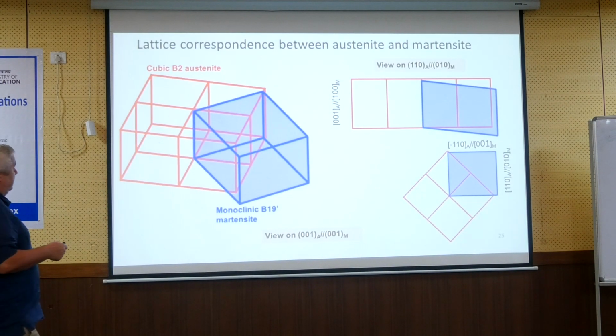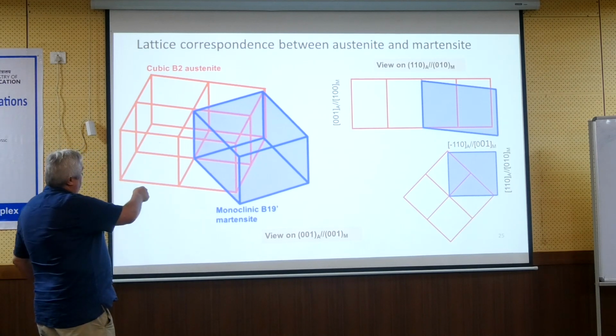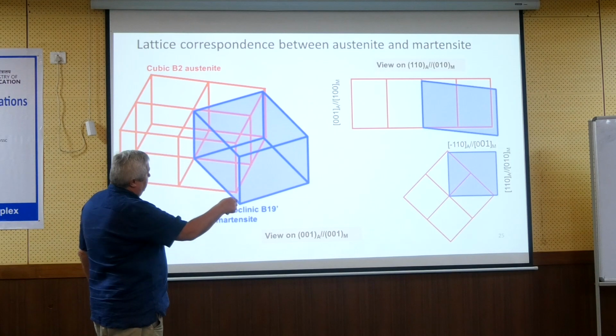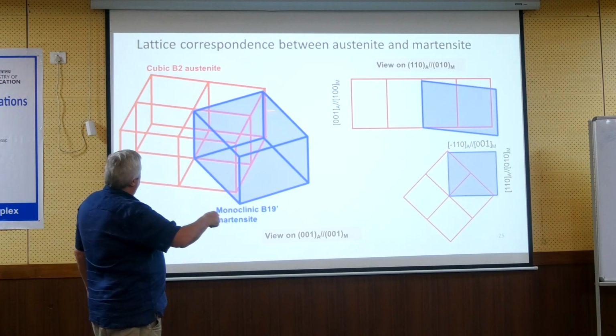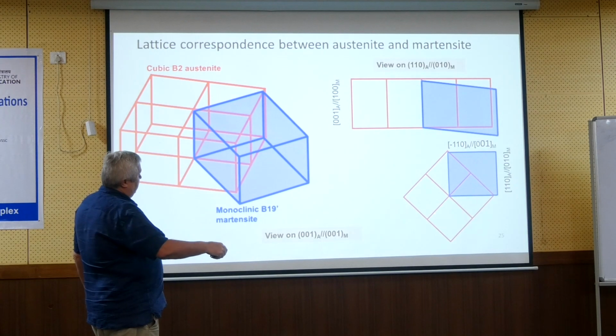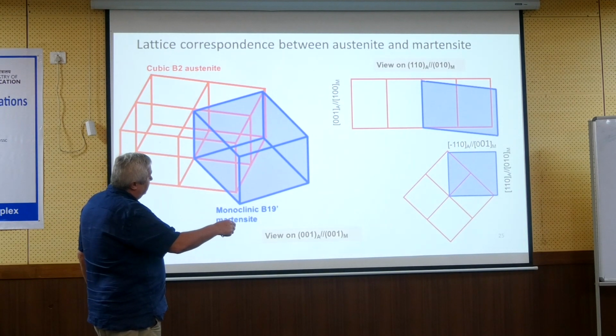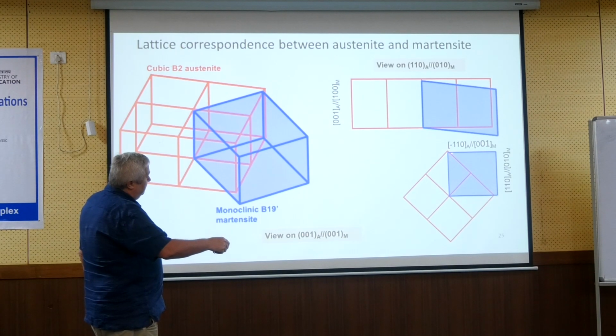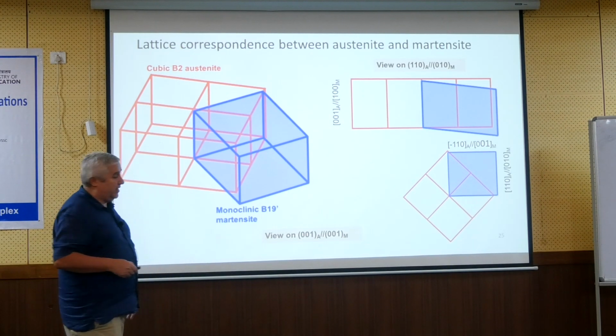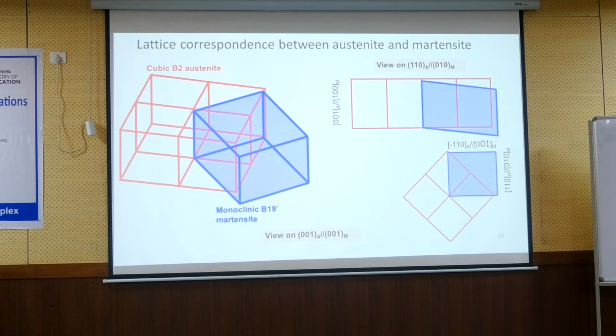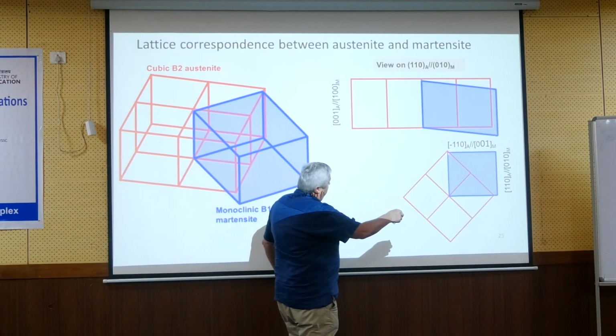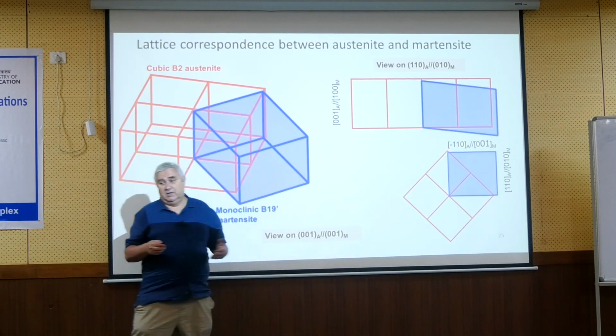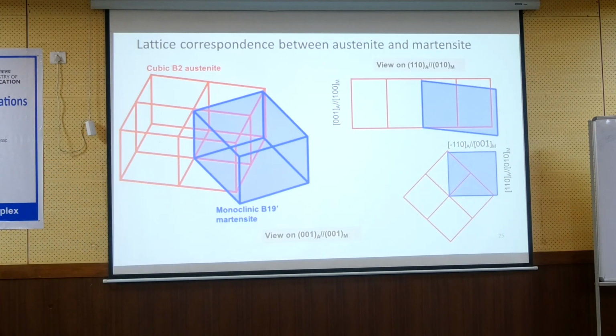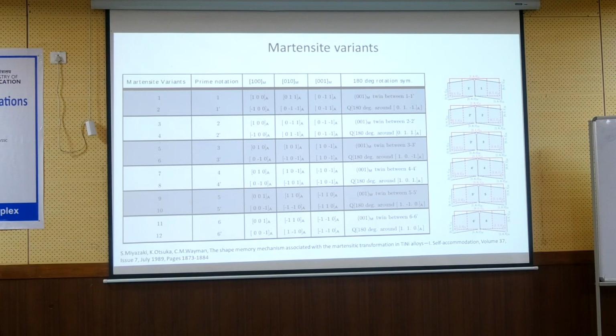Okay, so here it is. There was this animation which showed the change, and here it is plotted just 2 sections, and you see here this small misalignment. This small misalignment which is here, particularly this one here, which is this epsilon 2. This is this problem which the Chluba had, and which they solve by changing the lattice parameters in such a way that this red and blue are equal. In our case, they are not equal. And in our case, in NiTinol, they are not equal.